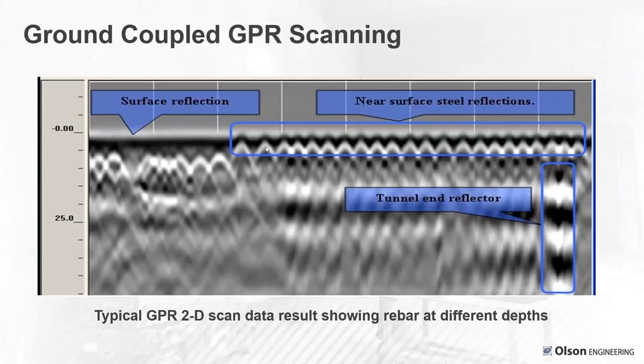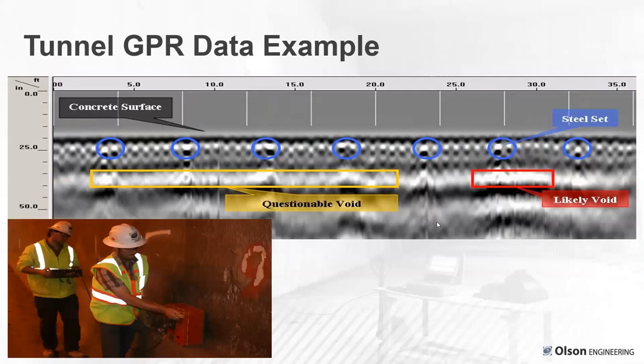Another example shows rebar right at the surface at the portal area of a tunnel — very shallow bars, quite different from the interior. Here's another GPR data example locating voids: the blue circles are steel sets expected about every 10 feet in the tunnel — they showed up nicely. But there's also a large bright spot reflector — that's very likely a void in or behind the tunnel liner, probably from water flow or some other feature.